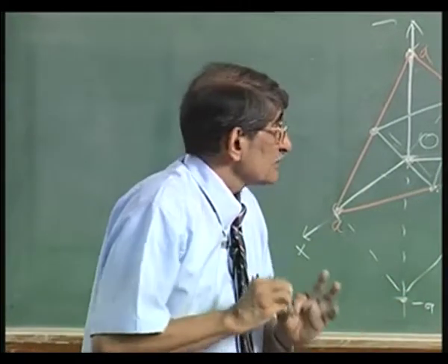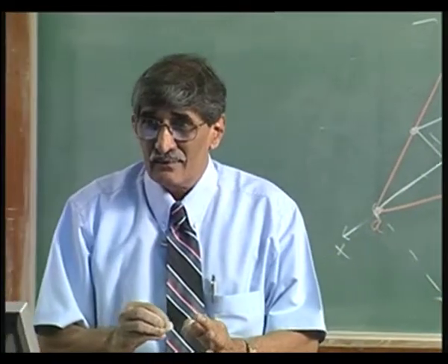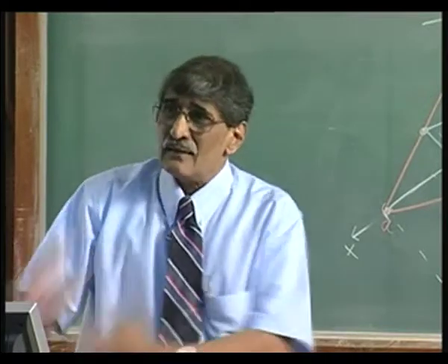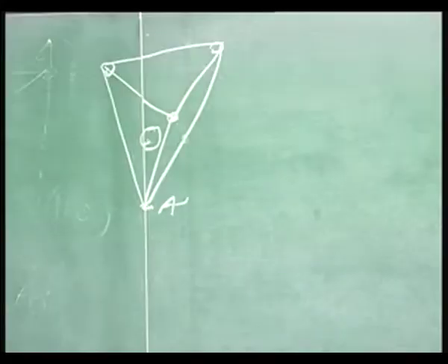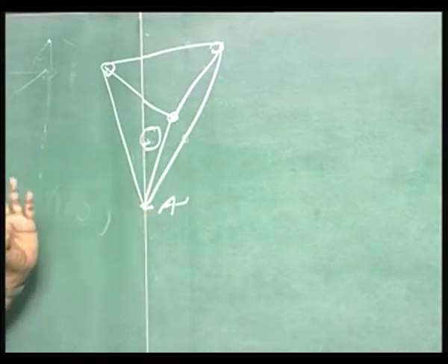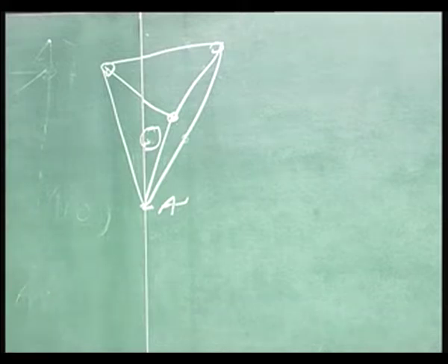So, you have a tetrahedral structure for gallium arsenide, and silicon also. In silicon, all of them are silicon, this is also silicon. That is where they say one silicon atom is sitting at the center of the tetrahedron. Here a gallium atom is sitting at the center. It is not necessary that gallium is sitting at the center of the tetrahedron, it can be arsenic with the 4 around that. Take a look at this now.